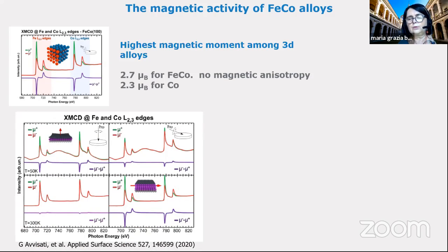In this case, I don't want to give you all the details. It was really complicated to intercalate both at the same time, iron and cobalt. It took half of a PhD thesis to realize this spin interface. But in this case, we realize a spin interface with a single layer of iron cobalt intercalated, a few layers. Then we repeat the XMCD experiment as I showed you before.